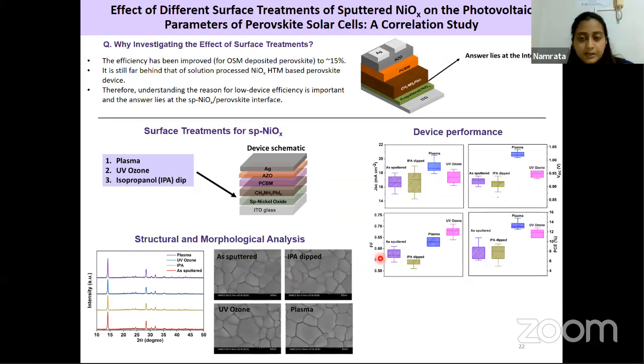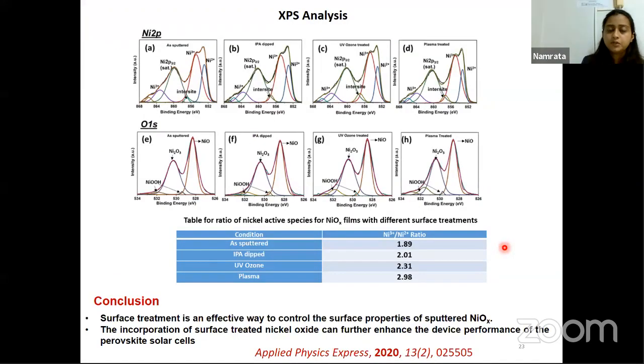So when we look at the device performance, and here is the box plot, we see that comparing the plasma treated nickel oxide with others, plasma treated has a much better performance. The JSC is significantly higher. VOC is much higher, and the fill factor, and of course the device performance. Just next to it is the UV ozone treatment. So definitely, even though we do not observe any change in the perovskite properties, we see a difference in the device performance. So it was important to understand the surface chemistry of nickel oxide after the treatment.